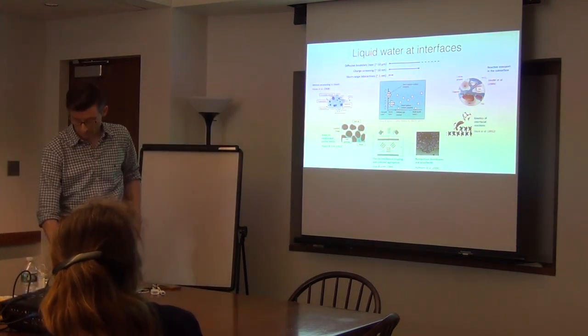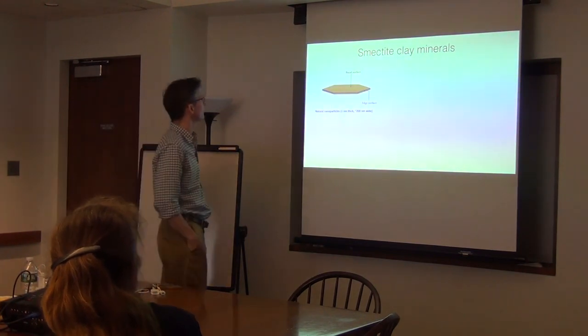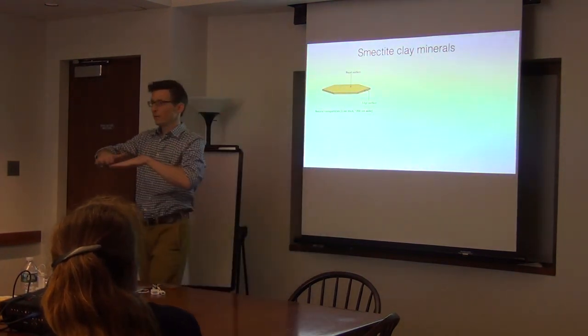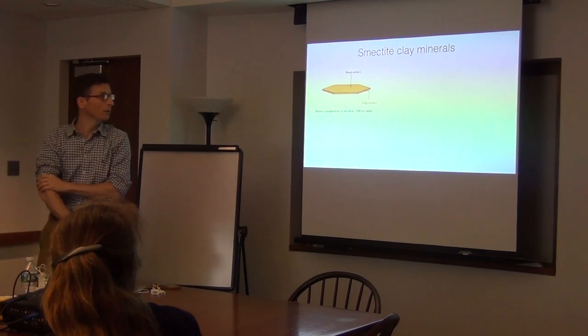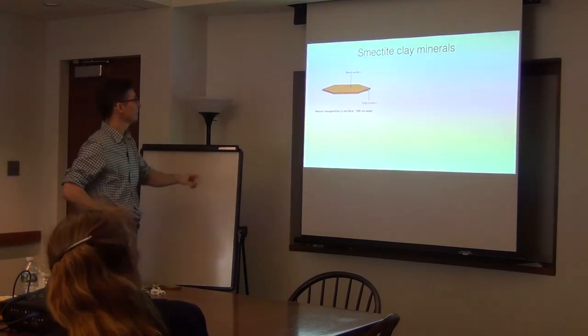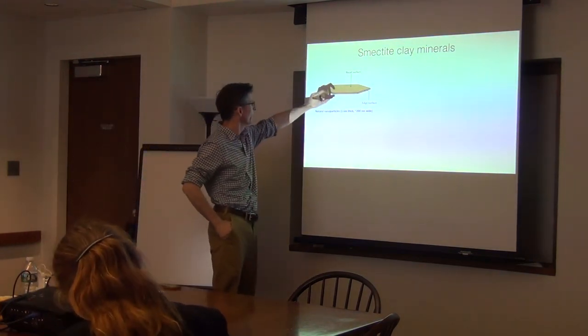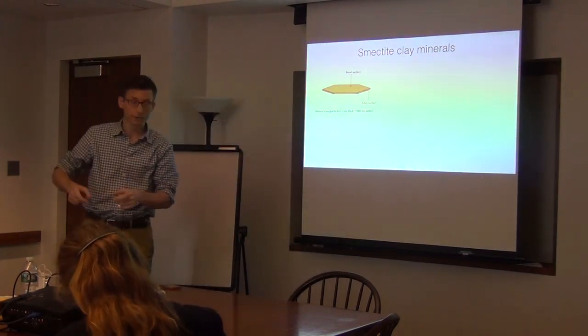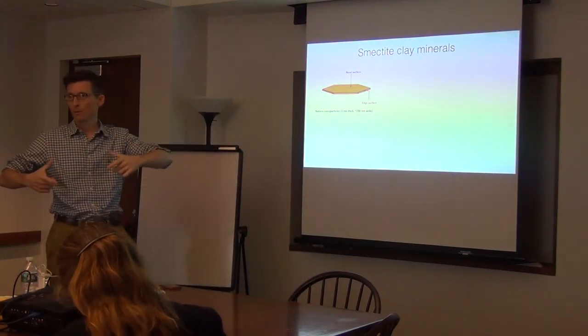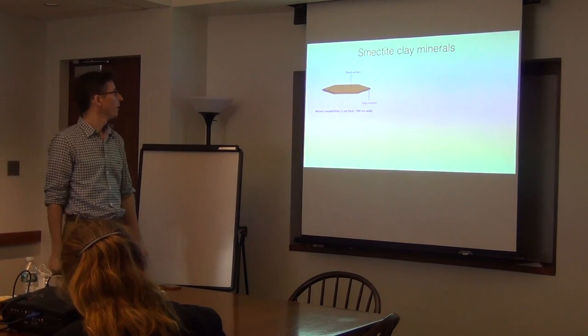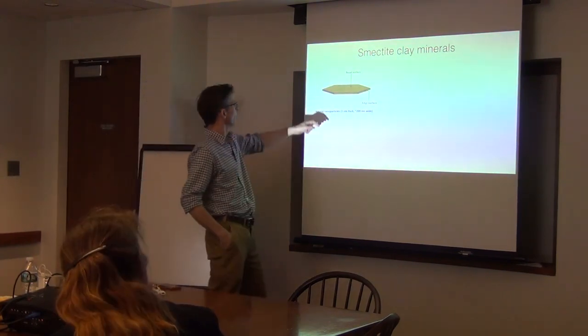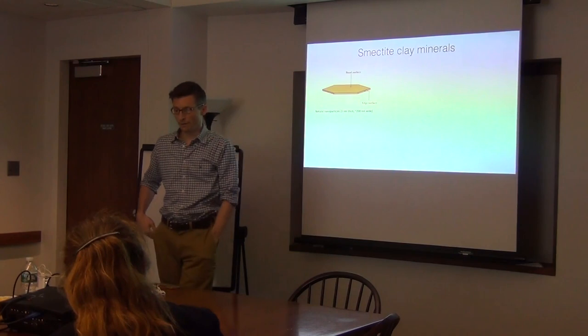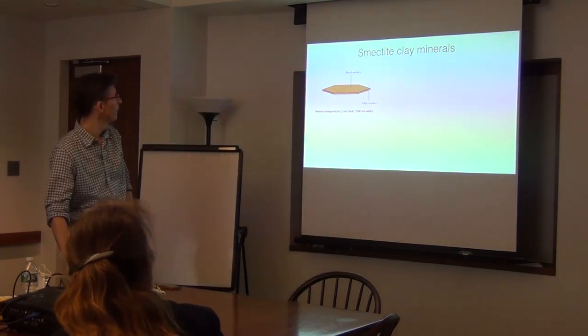Within this large sphere, what we mostly focus on is the way that water behaves on the surfaces of smectite minerals. These are little natural nanoparticles. They have a thickness of about one nanometer and form flakes. The diameters are on the order of maybe a couple hundred nanometers. You get a really high specific surface area here, about 800 square meters per gram.